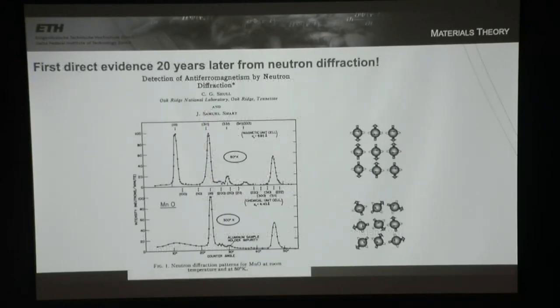So this took about another 20 years, and I'd say the first direct measurement came from neutron diffraction. And here I'm showing you the first data from 1950-something, 1954, I don't remember exactly. Sorry, I didn't put the date on. Of the neutron diffraction from manganese oxide above the ordering temperature, so when all of the manganeses are disordered, and below the ordering temperature when they're lined up in their antiferromagnetic state.